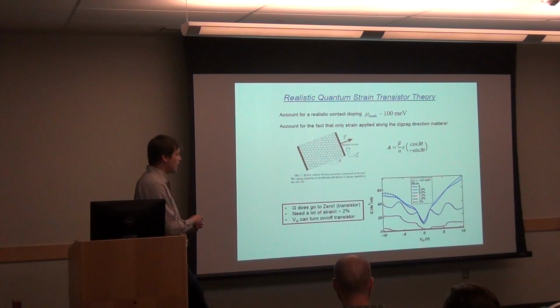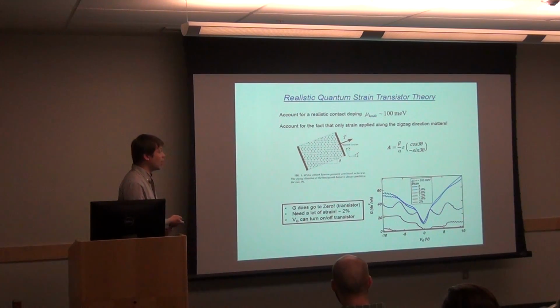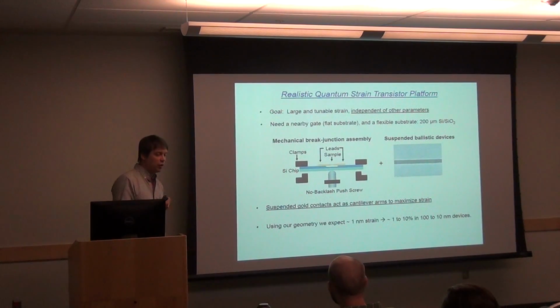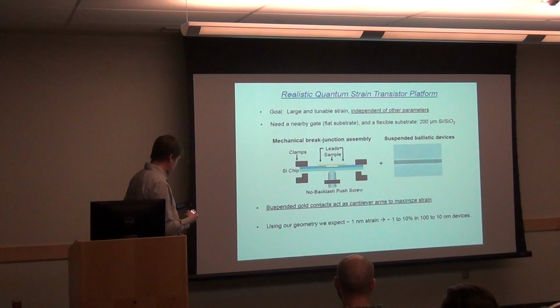So that's what we're trying to realize experimentally. The challenge though is that you can see that not much is happening actually up to 1% strain, and all the action happens around 1 to 1.2. And again, that's assuming that all of the strain is along the zigzag edge. So if you're not perfectly aligned, you might have to apply 2 to 3% of strain, which is tough to achieve experimentally.